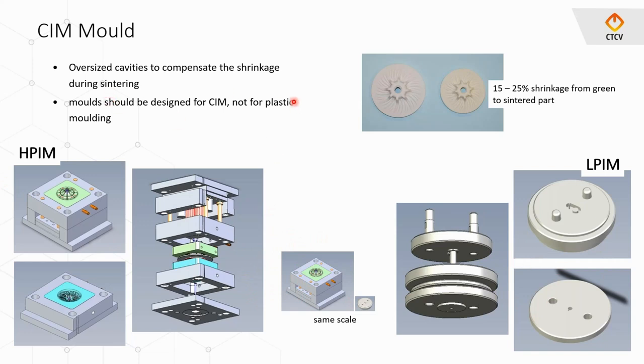So the cavities of the tool should be oversized to compensate for the shrinkage during sintering. You can see here an example of the range of shrinkage in alumina. We're talking about between 15 and 25% of linear shrinkage. And of course, if there is anyone attending this presentation from the plastic molding industry or from tooling, the tools are, let's say, 50% similar to plastic molding, but there is a critical aspect to change from the plastic world to the ceramic injection molding tool.